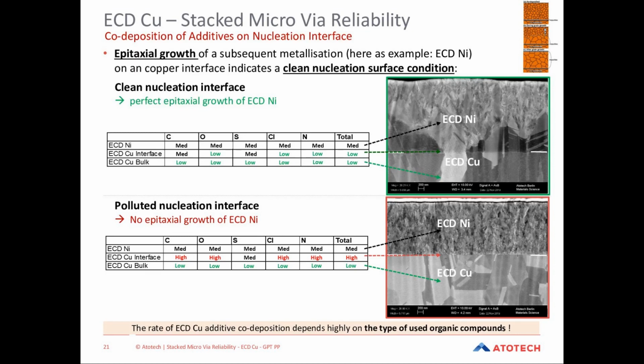It will from the beginning nucleate with its own crystal structure, and here you can expect that adhesion will not be the best between both metal layers, even if you don't see any gaps, even if you don't see any impurities or dark spots which could let you assume that there's some dirt. If the epitaxial connection between both metal layers is not given, you have to expect a poor bond, and in thermal mechanical stress situations, these layers might separate later very easily.